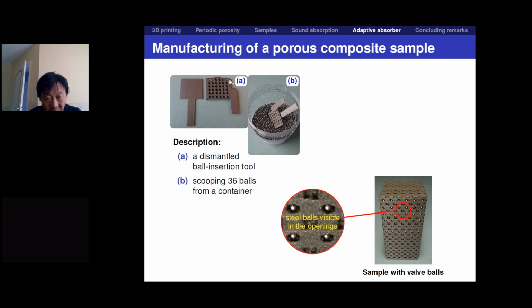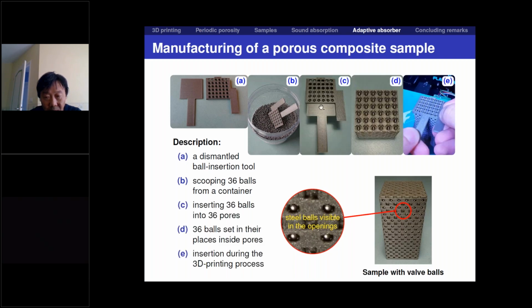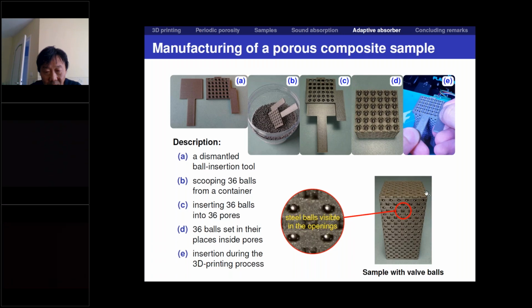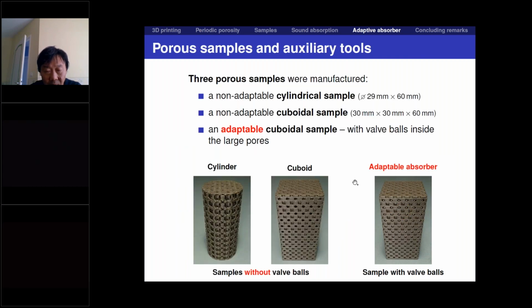I propose that we should first 3D print such a tray tool with which we can take 36 balls at once from the jar, and we can input them into the large pores very quickly. So here you have the sample with the pores, with the valve balls inside the large pores.